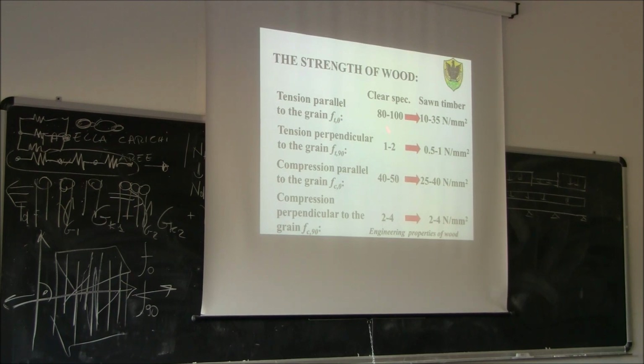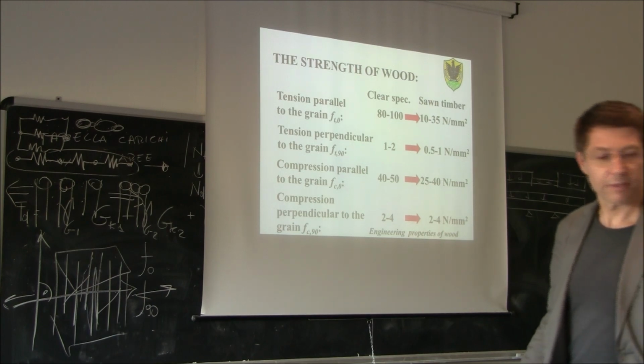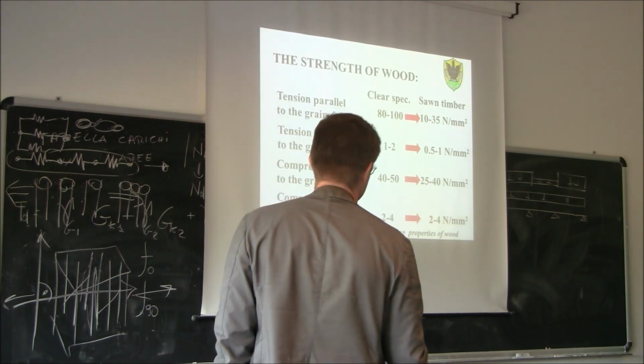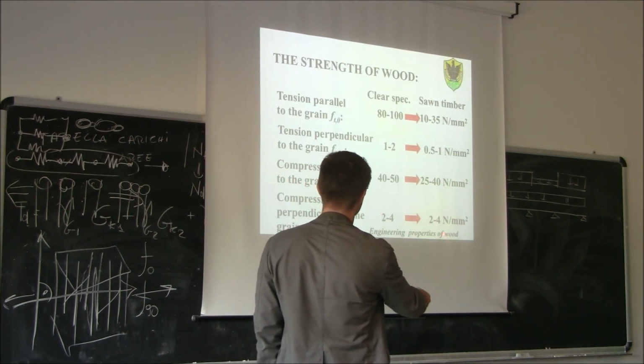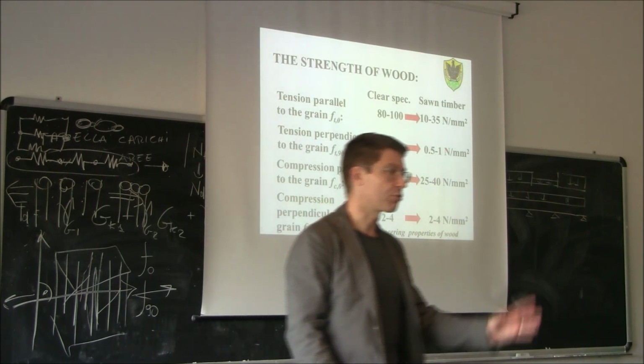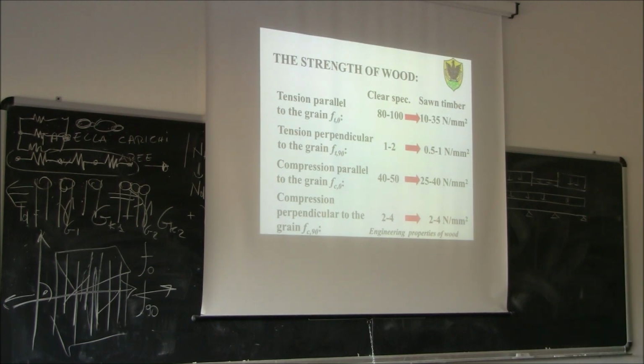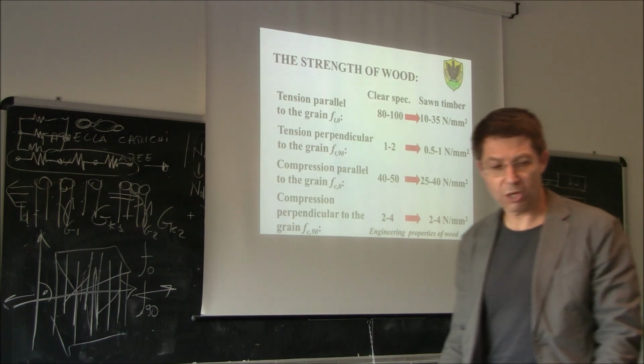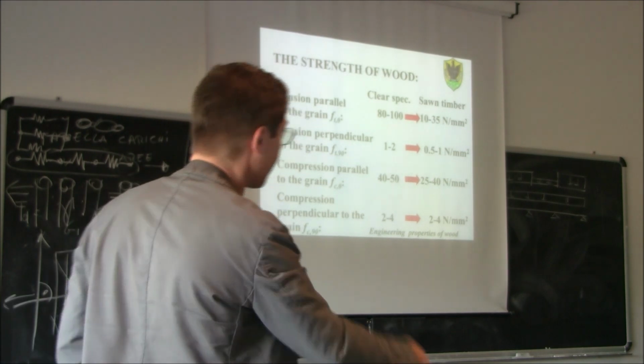So basically, while a clear specimen performs best in tension parallel to the grain, structural timber performs best in compression parallel to the grain. So for structural timber, the best property is no longer tension, but compression parallel to the grain. Tension parallel to the grain becomes the second best property, and then we have compression perpendicular to the grain and tension perpendicular to the grain. So when it comes to structural timber, we could say that tension perpendicular to the grain is practically zero. In fact, a good design criterion is always to ignore the tensile strength of wood perpendicular to the grain, because it's too low and too unreliable. Even though the regulation will give us a small value.